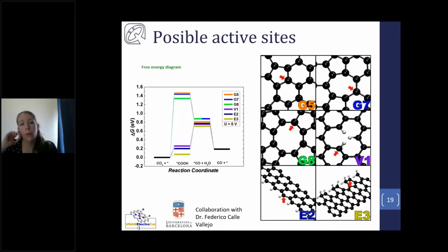One of my students went to do a stay with a collaborator, Dr. Federico Calle Vallejo at the University of Barcelona, and he started looking at different possible active sites for CO2 reduction on carbon. He came up with these 6 possible sites. We call these the geometric sites: the sites in rings that are not 6-member rings, so 5, 7, and 8. We also have some vacancy sites and some edge sites. All of these sites seem to be at least thermodynamically favorable for the CO2 reduction reaction at the potential we're working at in acetonitrile. So this shows the ability of carbon to reduce CO2 to CO.